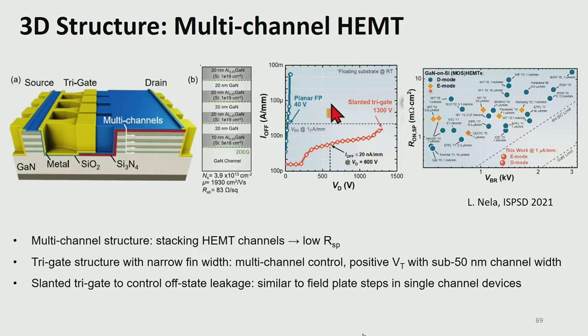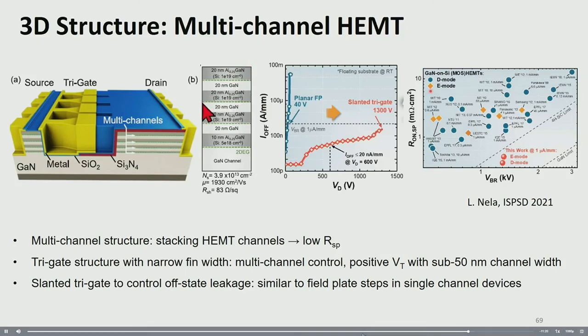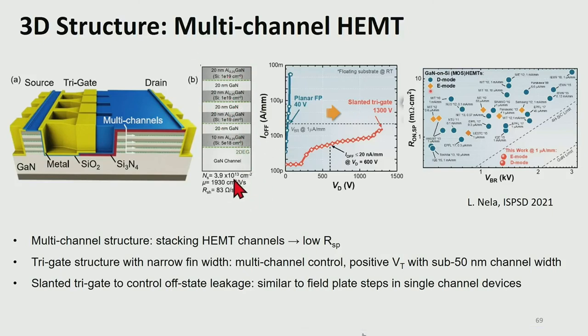And also, there has been continuous research on the new gallium nitride device structure. So similar to the silicon, 3D structure can provide additional freedom to improve the device performance in gallium nitride. For example, by stacking the heterostructures, multiple 2DEG channels can be formed, as you can see in this figure. And to control these multiple channels, the tri-gate and the 3D field plate concept were demonstrated, as you can see in this figure. And thanks to the multiple channels, this device shows a much better RSP while meeting the same breakdown voltage requirement. So this is one good example to show the new device structure can push the GaN technology performance significantly.